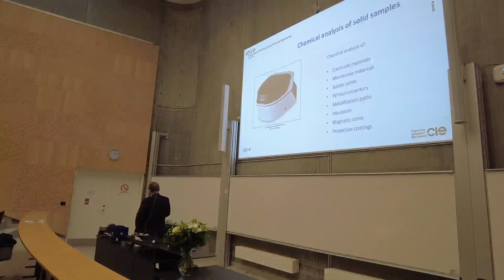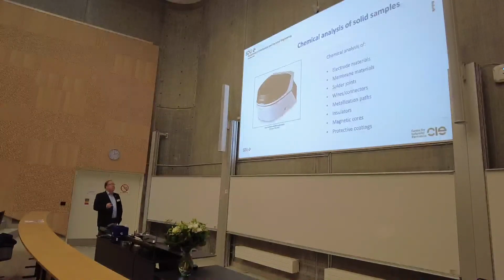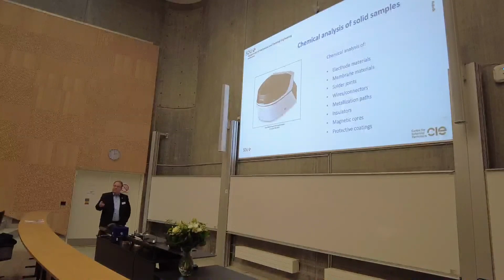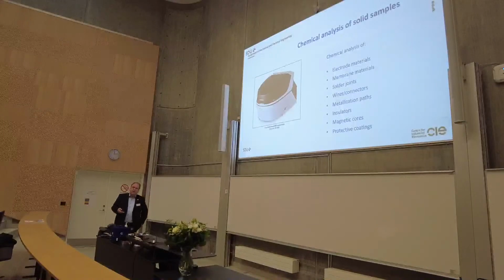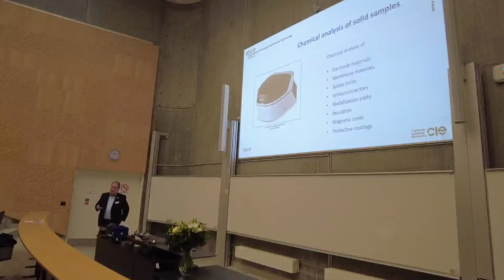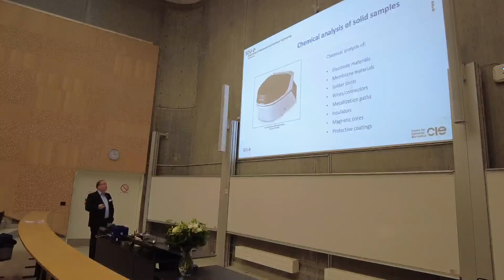When we speak about reliability, contact issues are also very often a root cause for failures. Therefore, we have to look into terminals. So we have invested in an XRF system, which allows us to investigate solders and solder metal compositions. So if you, for example, have a solder which is depleting in tin or getting certain defects, we can measure this with this tabletop instrument.